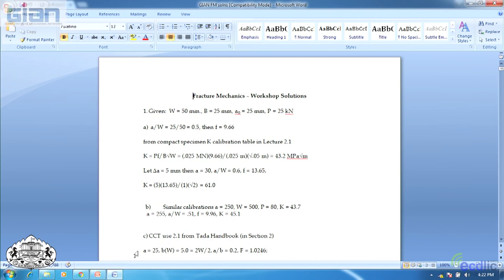Here are some solutions. If you're not finished, you can just follow along. And this will take us till the end of our time. Anyway, for the first problem, W is 50, B is 25, A is 25, load is 25 kilonewtons. You got to make sure you keep the units straight. You always start out calculating K's with A over W. So the crack length to the specimen width ratio is always important, because that tells you where to get on the table. Here it's simply 0.5. Then if you go to the table, the value says F is 9.66 rounded off. And put that all together.